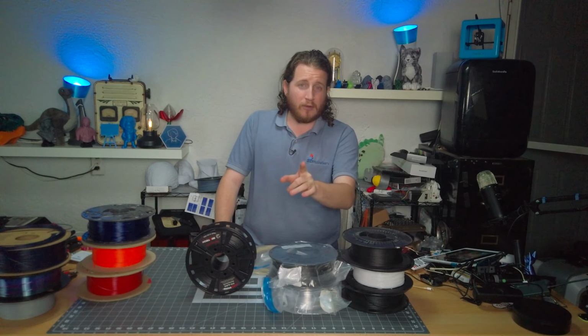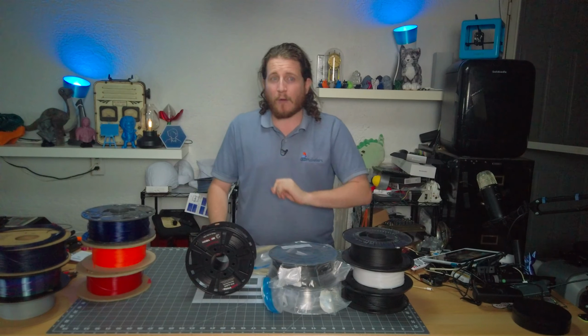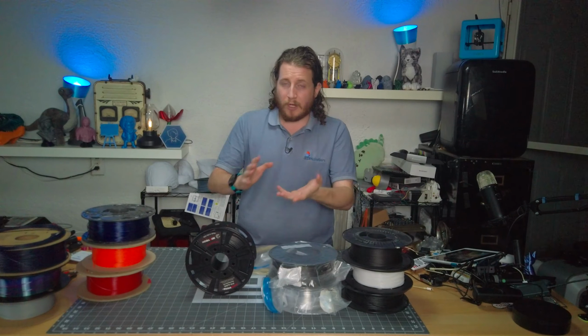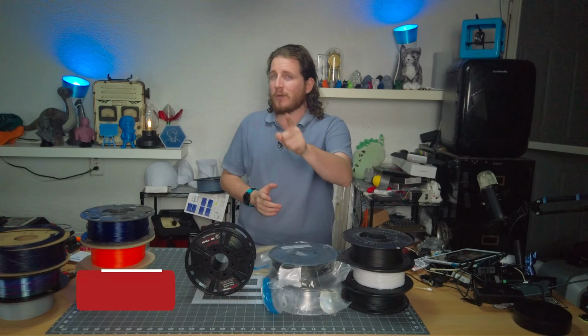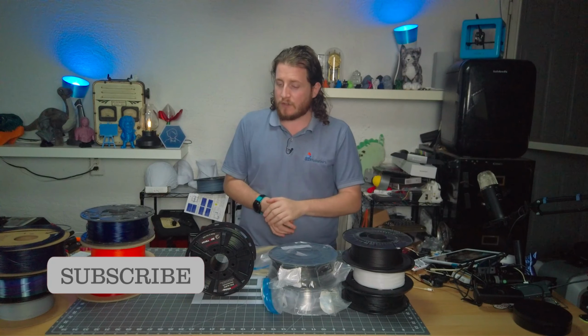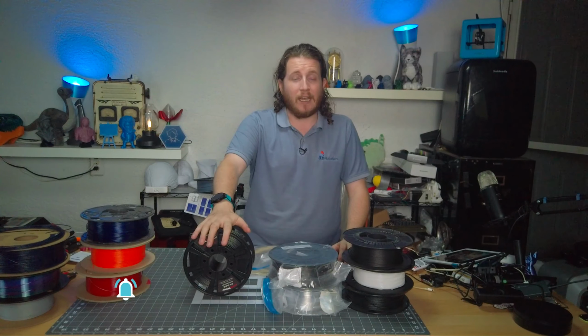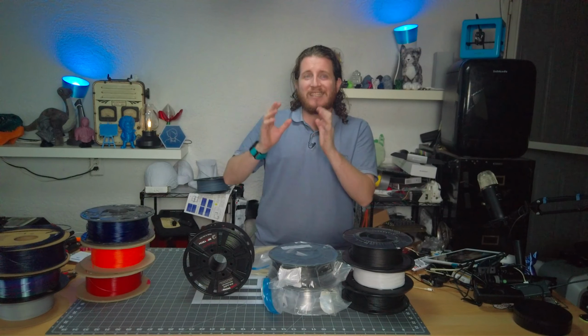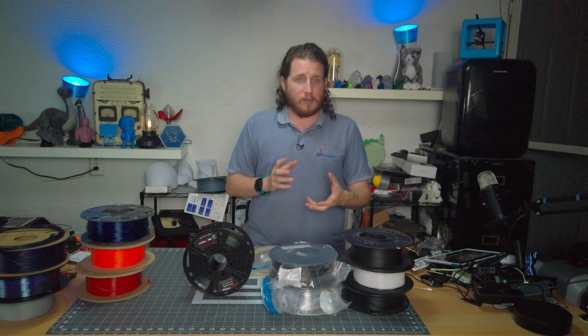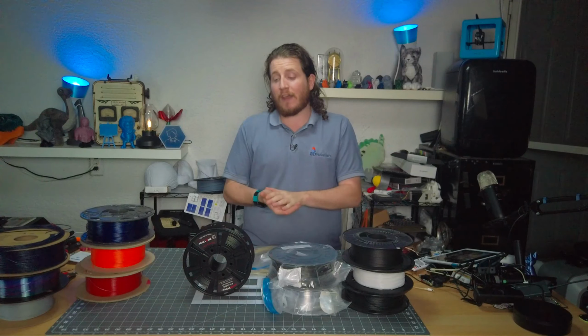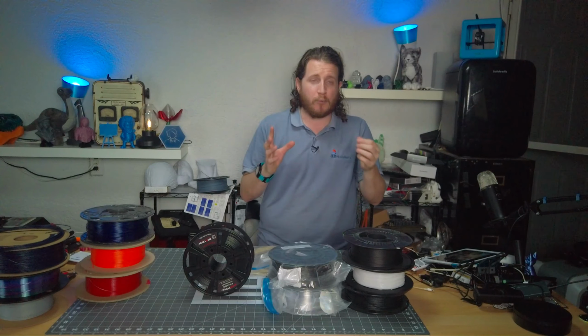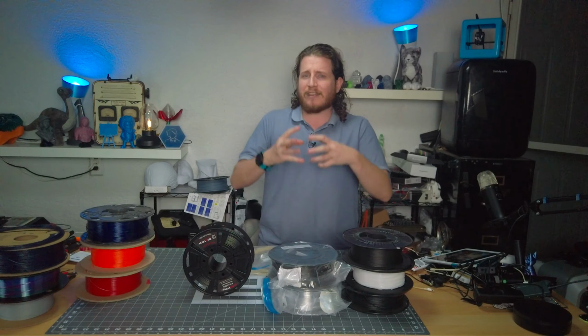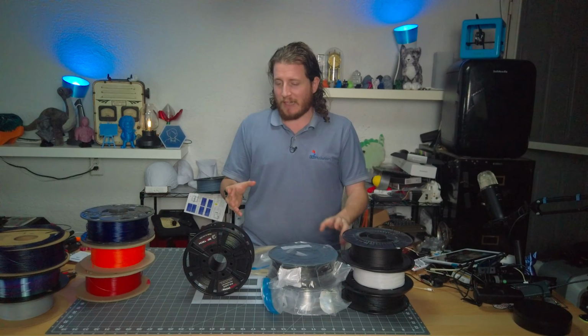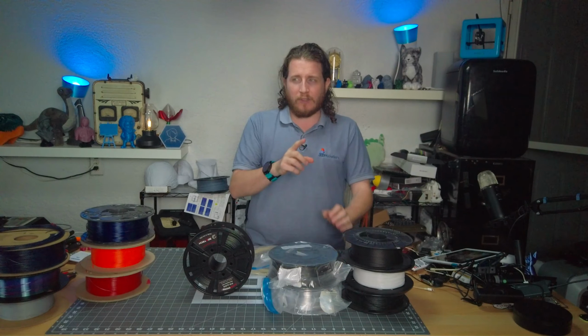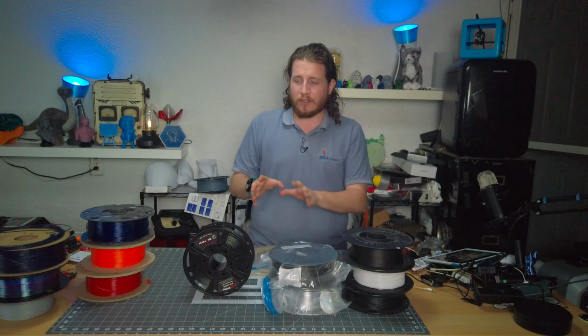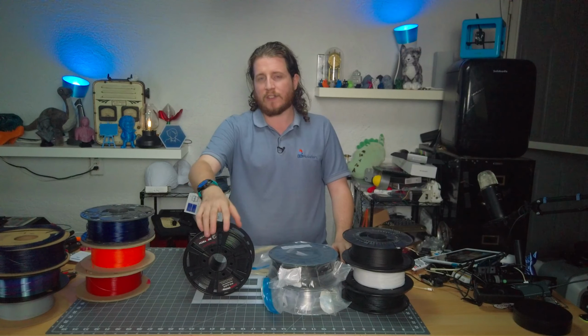But ABS particularly is very picky about orientation. Remember, 3D printing is weakest about the Z-axis, and we're gonna be doing a video on orientation coming soon. But this stuff is really tough because ultimately, it is not very strong on the interlayer bonds, and it is often recommended that you anneal it, which is a post-print baking cycle, to let the stress out of the filament itself. It will cause warping, so you have to be very careful if that's a thing you're going to do, because you have to really control the system well.